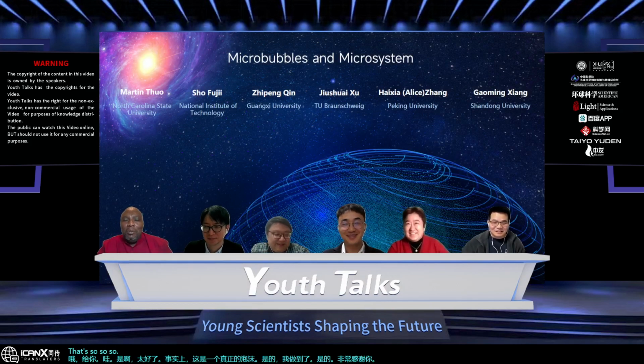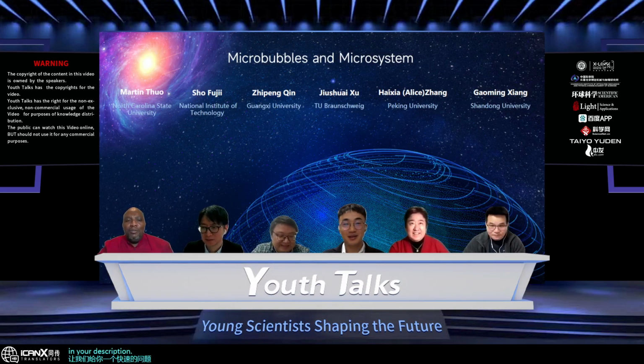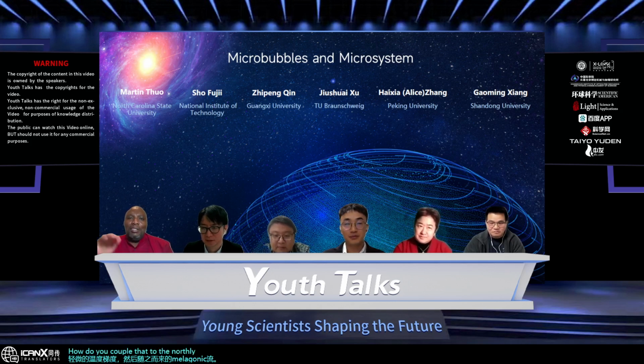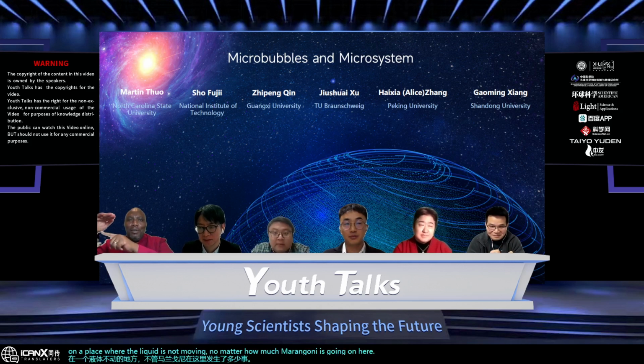So a quick question for you, in your description of the slight temperature gradient and the ensuing Marangoni flow, how do you couple that to the no-slip boundary condition on the gold surface? Because if your DNA is sitting on the surface, it's sitting on a place where the liquid is not moving, no matter how much Marangoni is going on here. So is the straightening of the DNA being driven by the shear force of the Marangoni flow?